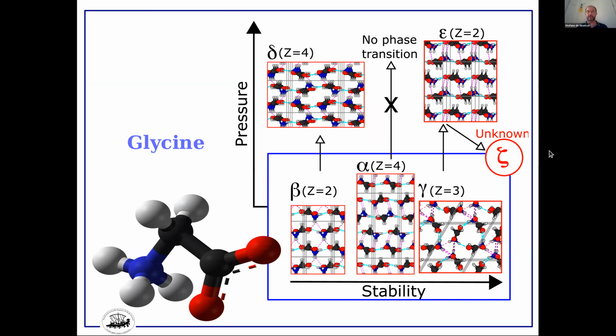But then if you apply external factors like pressure, for instance, so if you modify the external conditions, like you increase pressure, the beta phase may transform in another phase, delta phase. The alpha phase stays more or less unchanged for a while, up to the pressure that has been explored so far. But the gamma phase, for instance, is transformed into another one, which is called epsilon. And when you release the pressure, there is an additional phase transition to another phase that was up to recently not totally identified, not totally characterized, the so-called zeta phase.